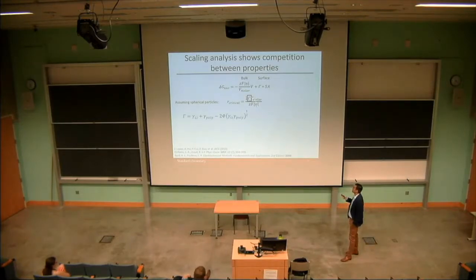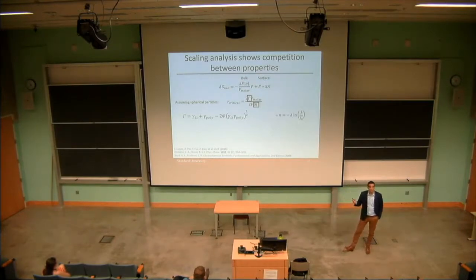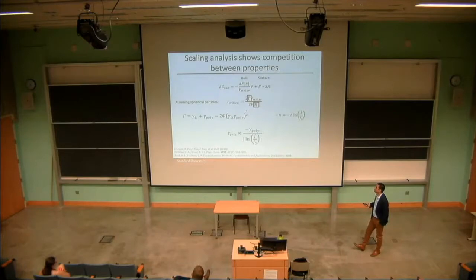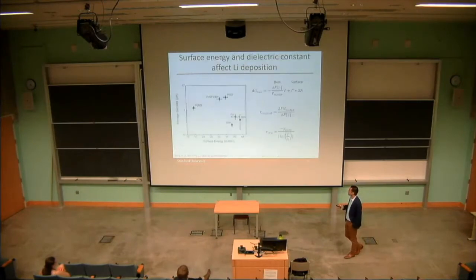And what we see is that, again, this is the interfacial energy, and this is a combination of the lithium surface energy and the polymer surface energy, and then the overpotential, which is just governed by the exchange current via the Tafel equation. And so this gave us a handle to really start to understand what properties of the polymer we should be looking at to understand this lithium morphology. If we do some scaling analysis, you do a Taylor expansion of this interfacial energy, you can end up that it's linear in the polymer surface energy, and then the exchange current shows up down here in the overpotential. So we started looking at these properties, and then again, this is just the same set of equations that I showed on the last slide. Looking at surface energy versus the average diameter that we take from those SEMs, we see very easily that there's some grouping, but not really a clear trend.